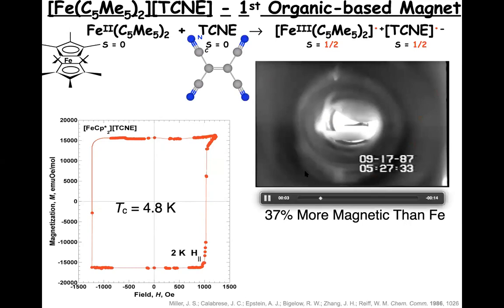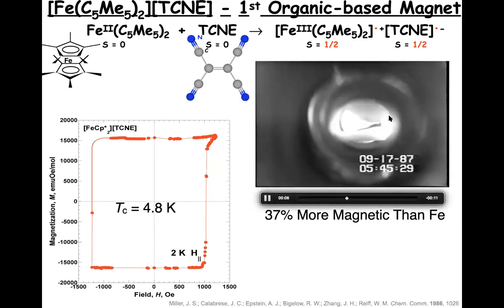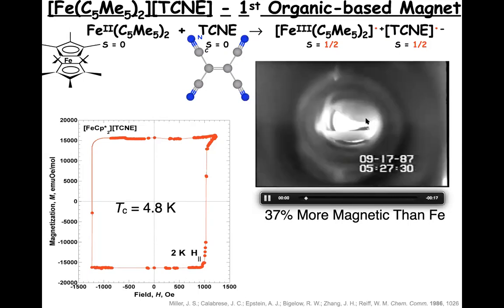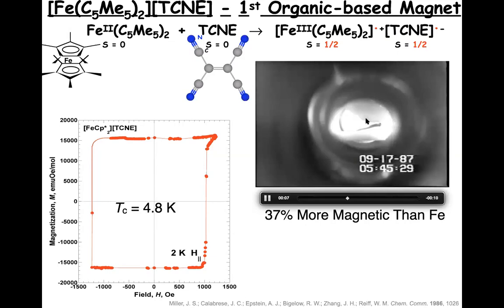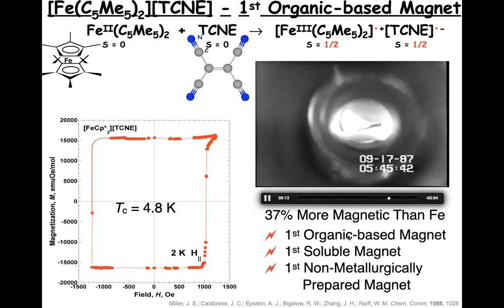And here we have a slab of it on a piece of Teflon in an optical window, and we put in liquid helium. It gets cold. When it gets cold, it gets very magnetic. And when it gets magnetic, it's going to jump up to this cobalt samarium magnet, as you just saw. And when you let the helium boil away, it gets warm above TC and drops down. So this material over here is the first organic-based magnet.